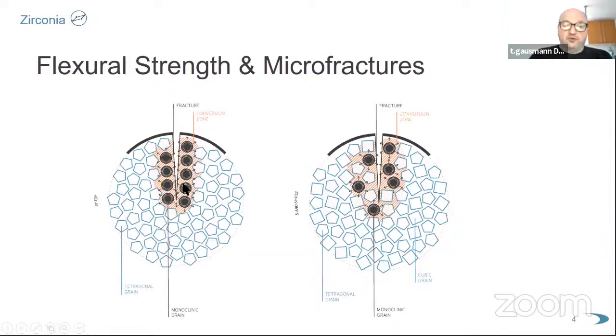And in the end, the beauty of the material in general, in zirconia, that is what makes it so tough and hard, is that it will compress the crack at a certain point where you've got enough tetragonal material changing to monoclinic material. So then the crack is compressed in the end at the tip and stopped. So the crack can't go through the material like in normal window glass or something else. So that is a good thing about this modification.